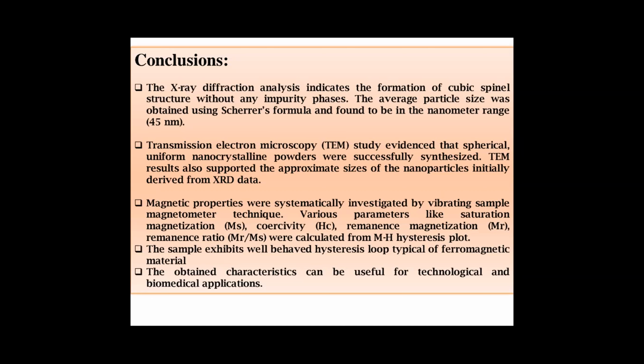Magnetic properties were systematically investigated by vibrating sample magnetometer technique. Various parameters like saturation magnetization, okay, HC, remanence magnetization, MR, okay, and remanence ratio MR upon MS were calculated from MH hysteresis plot. Okay, then the sample exhibits well-behaved hysteresis loop typical of ferromagnetic material. The obtained characteristic can be useful for technological and biomedical applications.